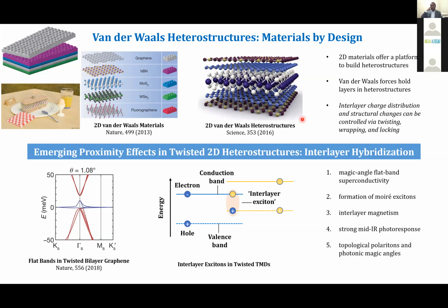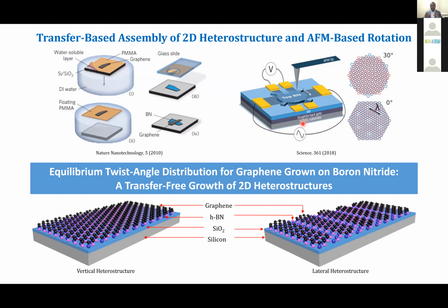So therefore, this study is important and recent, and I'm going to show some from my research on how we are building these kinds of structures without using any transfer that I discussed earlier, and we are also able to rotate these structures. So traditionally, these materials are placed one on another, as you can see here. This is a polymer-based transfer where you can put graphene or boron nitride on a silicon oxide substrate first, and then take graphene and put it on boron nitride, and then use an AFM tip to rotate these materials to get the angles, as you can see here.